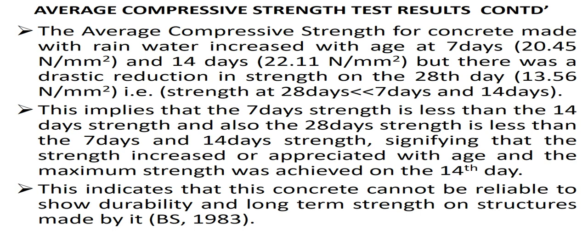22.11 Newton per millimeter squared, but there was a sharp, drastic reduction in strength on the 28th day. That is 13.56 Newton per millimeter squared. That is, strength at 28 days is far less than that of 7 days and 14 days. This implies that the 7-day strength is less than the 14-day strength, and the 28-day strength is less than the 7-day and 14-day strength, signifying that the strength increased with age, but the maximum strength was achieved on the 14th day. This indicates that this concrete cannot be relied upon to show durability and long-term strength on structures made with it.